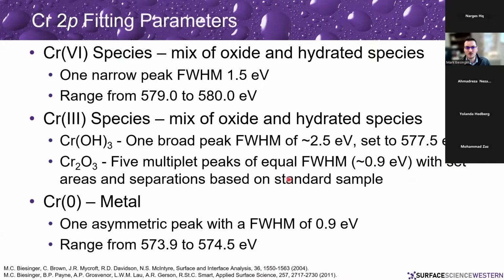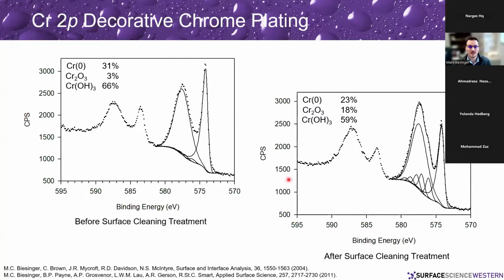And we set up rules for how to do this curve fitting. So for chromium 6 species, we're going to have one narrow peak ranging from 579 to 580 eV that will model the chromium 6 species present. We'll model the chromium 3 species, one set of peaks for the chromium 3 oxide and a peak for chromium 3 hydroxide, again all well constrained and within a specific binding energy range. And then for the metal, we're going to have an asymmetric peak shape assigned. And when we apply this to unknown systems, we can pull out how much of the different species we have present. And it can pull out very small and subtle changes for that matter.